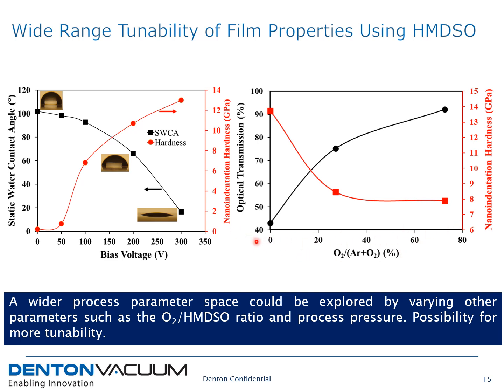By increasing the oxygen ratio, you can see that the optical transmission increases from about 40 to all the way up to 90%, and the nano indentation hardness decreases from about 14 GPa down to about 8 GPa. So the film can be actually tuned from a hard DLC-like coating all the way up to a silica-like coating. In fact, a wider process parameter space could be explored by varying other parameters like the oxygen HMDSO ratio and the process pressure. So there is scope for more tunability.